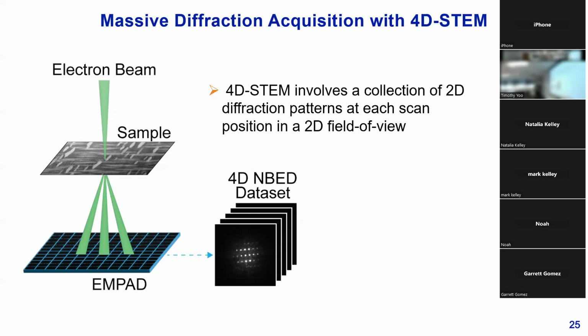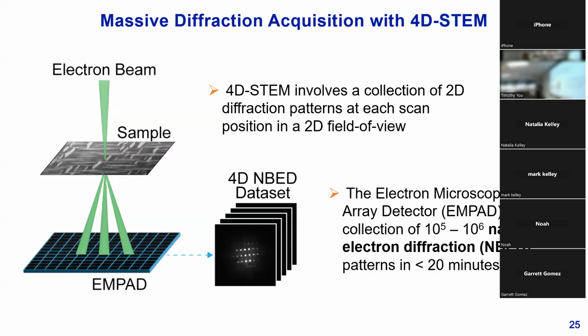So 4D STEM has a similar setup with your beam, where you have your relatively focused electron beam scanning across your surface, but at every position in a 2-dimensional field of view, you're acquiring a 2-dimensional diffraction pattern. 2D plus 2D gives you that 4D. And this results in a stack of diffraction patterns that's spatially resolved. This is thanks to a special direct electron detector that we have here called the electron microscope array detector.